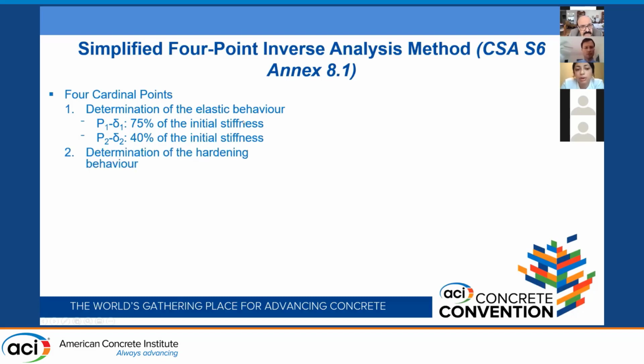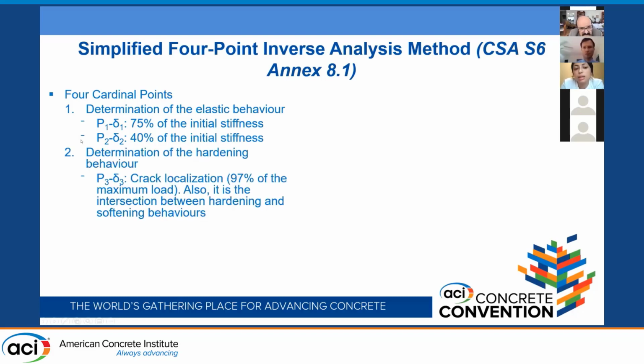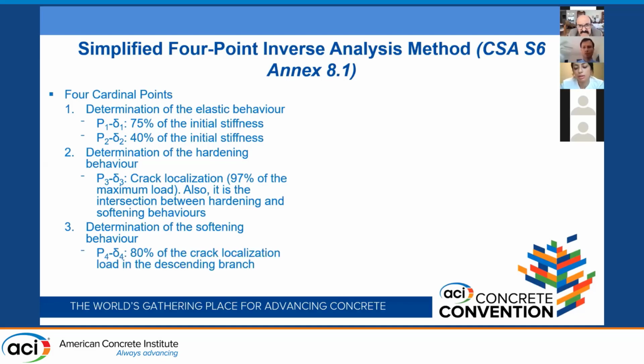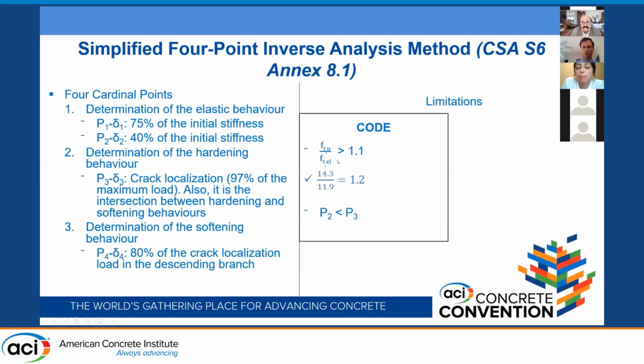The third point is for the hardening behavior, and it's the crack localization point. Here it's taken as 97% of the maximum load. It's the intersection, or the border point, between the hardening and the softening behavior. The fourth point is from the softening behavior, and it's 80% of the crack localization point. Now this method, just like any other method, has its limitations. As per the code, the material has to be hardening, which means the ultimate strength has to be at least 10% higher than the elastic strength, and this is satisfied for the material we're using in this research.